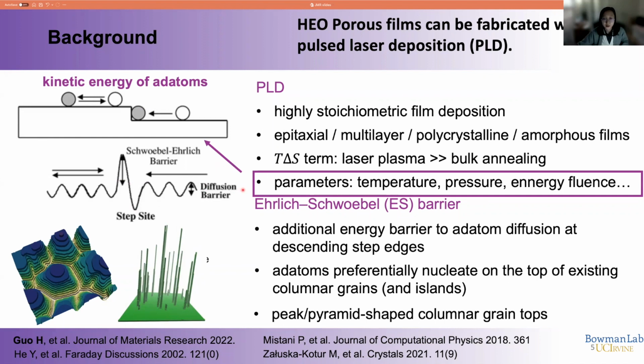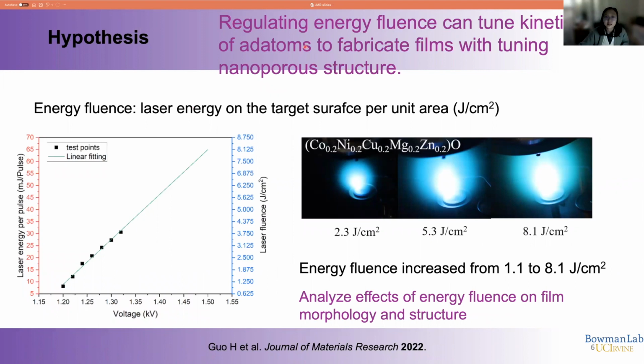So in this work, we want to control the parameters of PLD to control the kinetic energy of atoms to achieve fabricating HEO porous films. Our hypothesis is regulating energy fluence can tune kinetic energy of atoms to fabricate films with tuning nanoporous structure. We use the energy fluence as the parameter to control kinetic energy of atoms. Energy fluence is defined as laser energy on the target surface per unit area, as you can see in this image.